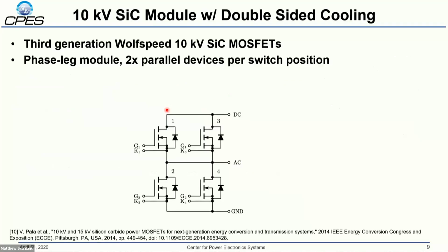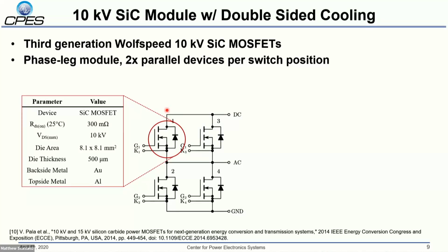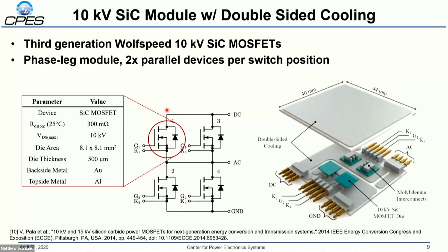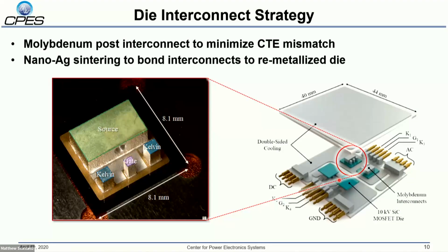So next, I'll briefly go over some of the module details. This is a phase leg module that's based on third generation 10 kV silicon carbide from Wolfspeed. We've got 4 devices in there total, 2 in parallel per switch position. So you can see an exploded view of the module here on the right with the 4 devices located inside. These 4 devices are sandwiched in between 2 aluminum nitride substrates that serve as the top and bottom cooling surfaces. The devices utilize a molybdenum post interconnect in place of more conventional wire bond technology. So this is really what's enabling us to pull the heat out of the top of the die and exhaust it through that top substrate.